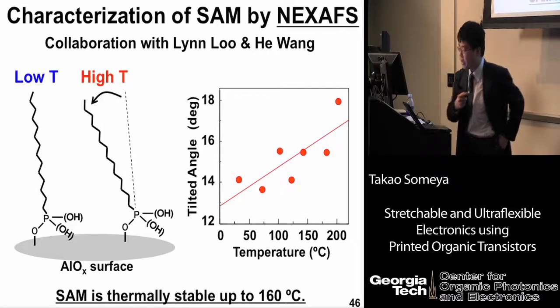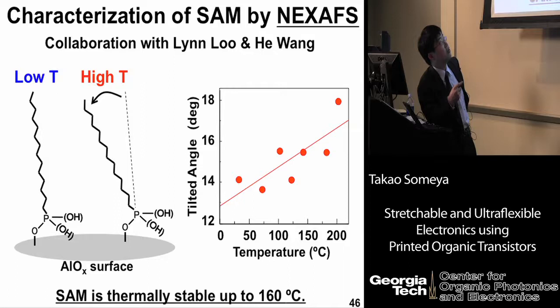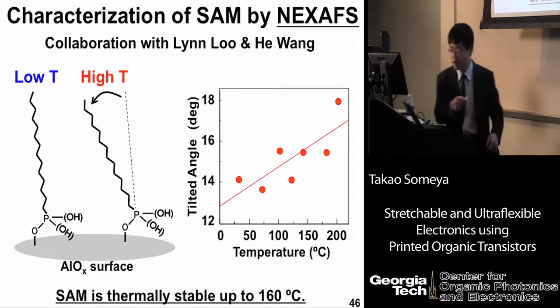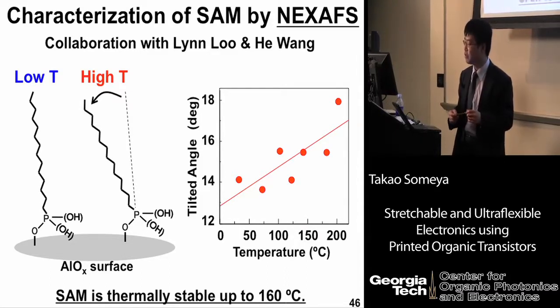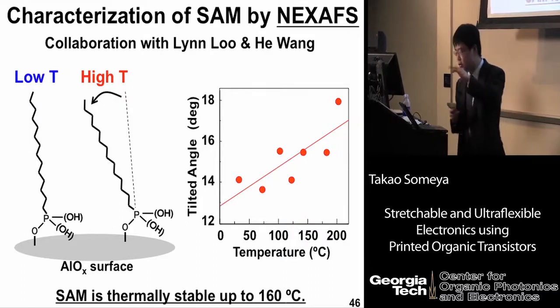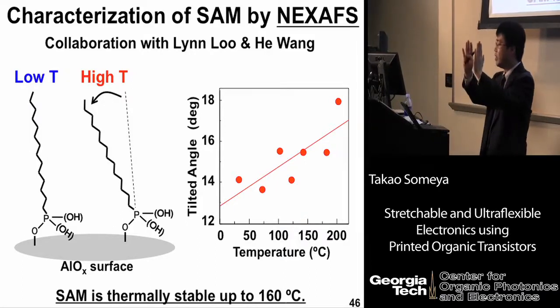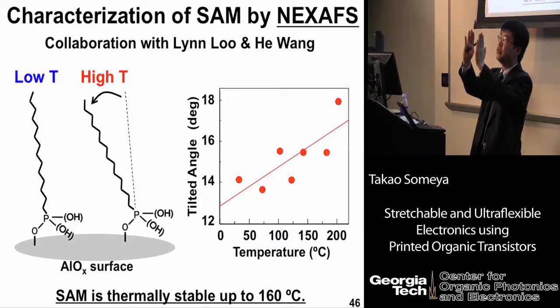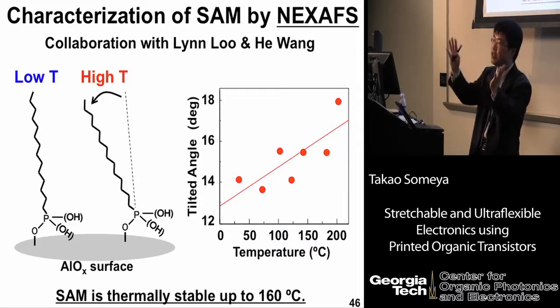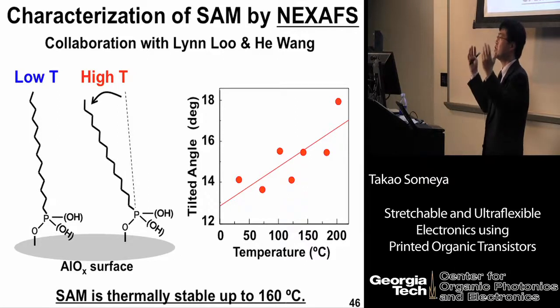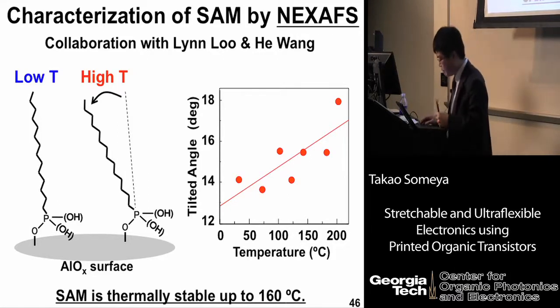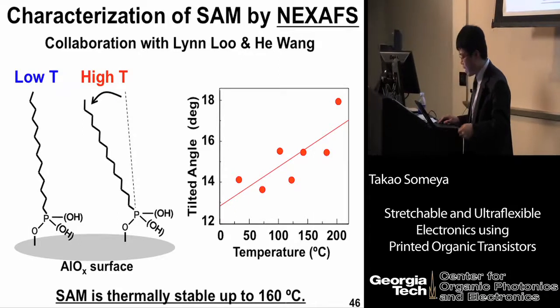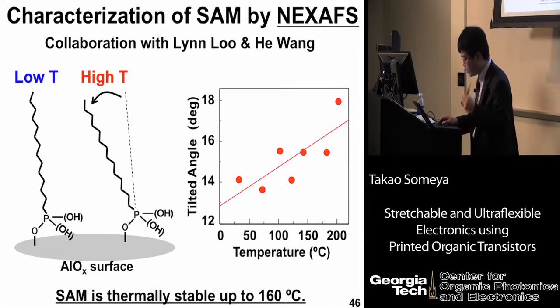Indeed, we measured the tilt angle of the self-assembled monolayer as a function of annealing temperature by using NEXAFS. This experiment was done in collaboration with Professor Lynn Loo at Princeton University. With elevating temperature, the tilt angle slightly increased, but there is no drastic degradation. So in this way, we could confirm how thermally stable such a thin self-assembled monolayer is at high temperature.